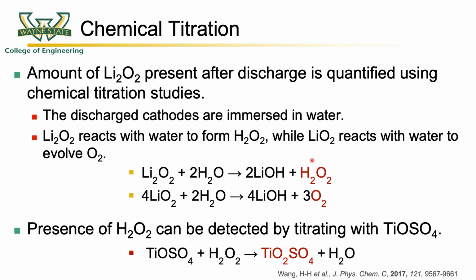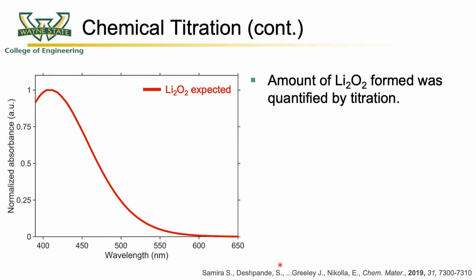The amount of titanium oxysulfate that changes color is determined using UV-vis spectroscopy. If all the discharge species on a discharge electrode were Li2O2, this is the curve that you would expect using UV-vis spectroscopy.